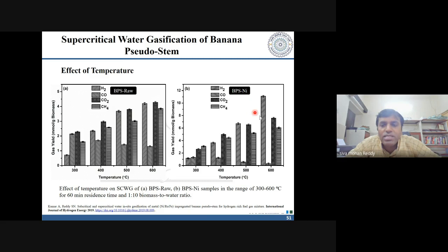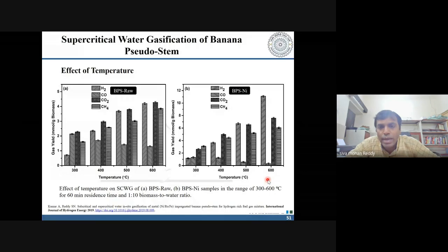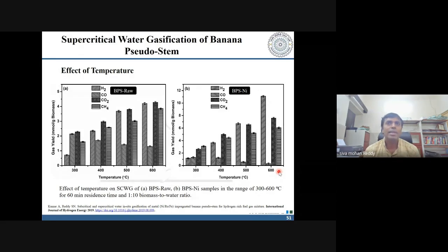Now, as soon as you are increasing your nickel content, you see that the quantity of your carbon monoxide is almost negligible in case of nickel impregnated banana pseudostem at 600 degrees centigrade, which conveys to us that the nickel has selectively promoted the reforming reactions, thereby enhancing the hydrogen gas yields significantly, that is nearly 11.1 millimole per gram. And not only that, it also increased your carbon dioxide yields, which conveys that it is selectively promoting the reforming reactions, and thereby enhances the overall gas yields that we are looking for.